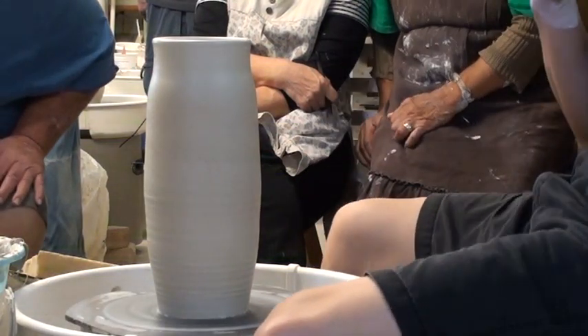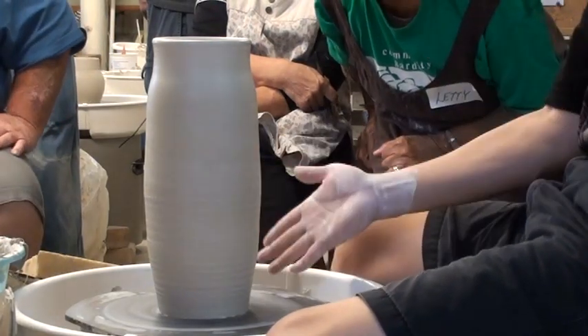See that start to crack. Different texture, you get a different feeling. I put the bottom and the top as the contrast for you. So, when you applied the sodium silicate, did you do an even coat top to bottom? Could you do some spots a bit thicker? Yes, the thicker one, you will get a thicker crackle pattern.